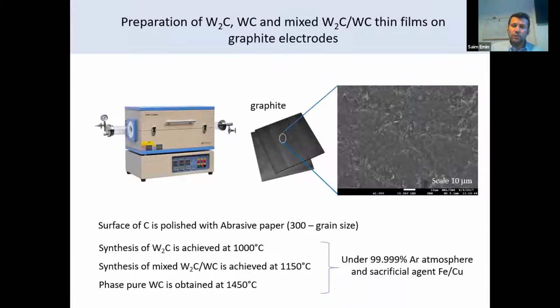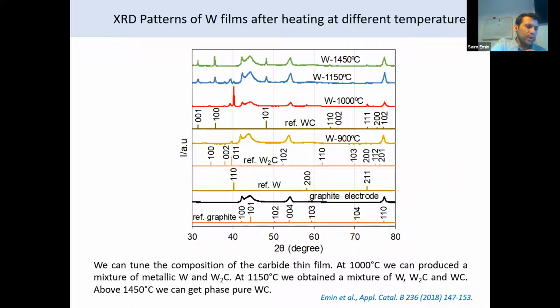What we did is we coated these electrodes on graphite. Some of the studies were also done with FTO, fluorine-doped tin oxide, but graphite is cheap, so we took this graphite, cut it in pieces, put it in the tube furnace and heated at high temperatures. And we were able to make different phases of tungsten carbide. Here you can see the reference, which is W2C. This is one phase of tungsten carbide. Another is WC. These peaks are the reference, and at high temperature we can grow the phase with the high carbon content, which is WC.